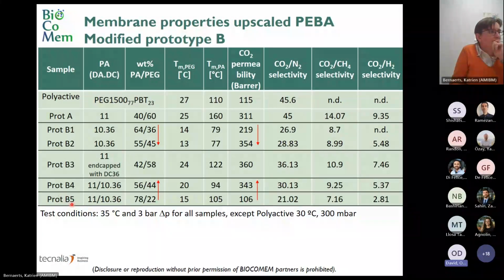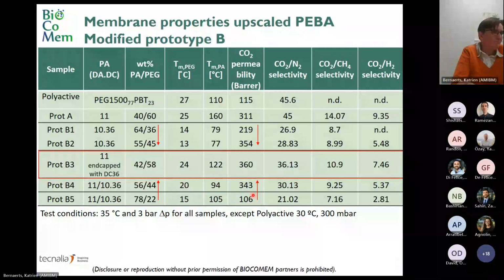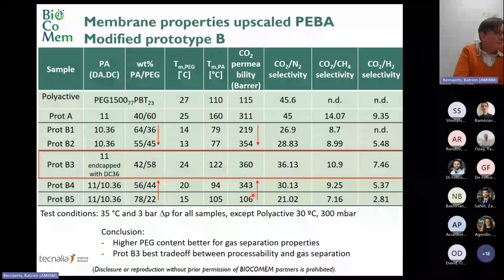And then we have prototypes B4 and B5. B4 is also a good polymer for carbon dioxide permeability. And B5, we use as a porous support polymer, and I will show later in the hollow fiber processing why it was done that way. So it has more polyamide part, and the permeability for carbon dioxide is lower, but we didn't use it to make a membrane. We use it to make a porous support. And as you can see, the overall best polymer is this prototype B3. So from these experiments, we can conclude that a higher PEG content is better for the gas separation properties.